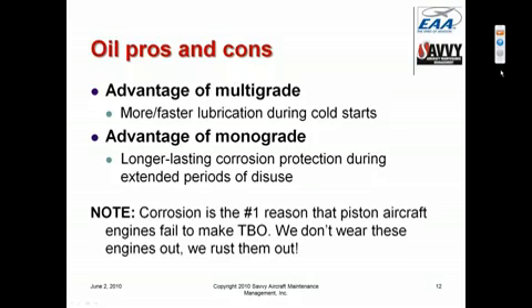You can see that for yourself after shutdown. If you check how long it takes for the oil level to come up and stabilize on the dipstick after the engine is shut down, multigrade oil tends to stabilize within a couple of hours after shutdown. Monograde oil can take days before the oil level comes up and stabilizes after an engine shutdown, simply because the oil film is much gooier and thicker and takes a lot longer to strip off the parts. And we want it to stay on the parts to provide corrosion protection.